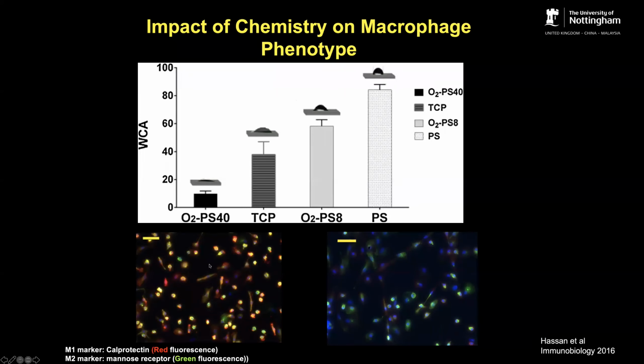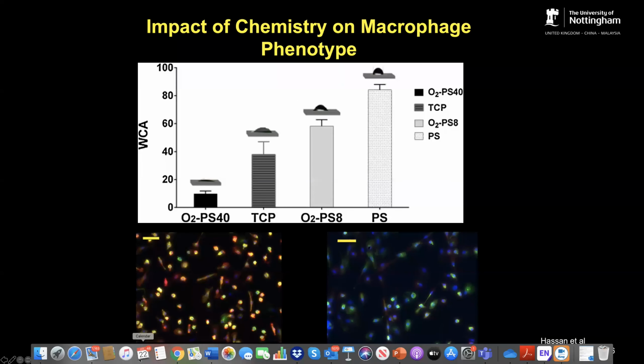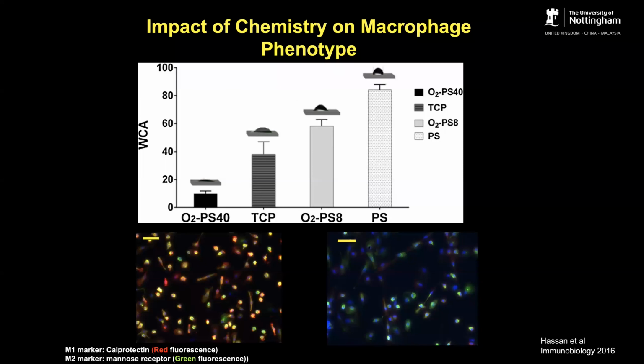And from those experiments, what we saw was that the cells cultured on hydrophilic surfaces acquire this pro-inflammatory phenotype. Here we are looking at the surface phenotype of these cells, and the red color represents calprotectin, which is a pro-inflammatory marker, and the green dye represents mannose receptor, which is an anti-inflammatory marker. You can see that cells on this hydrophilic surface express higher levels of calprotectin. They have acquired a pro-inflammatory phenotype, and this is quite in contrast with cells on the hydrophobic surfaces, which express high levels of the anti-inflammatory marker mannose receptor and very low levels of the pro-inflammatory marker. So we are able to differentially polarize these cells by simply changing the surface chemistry, using plasma etching at different levels.